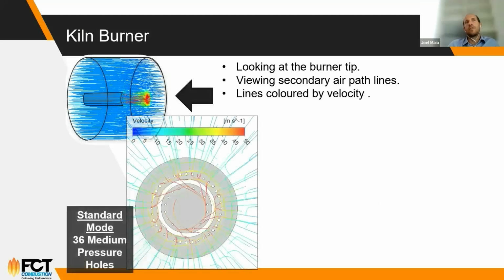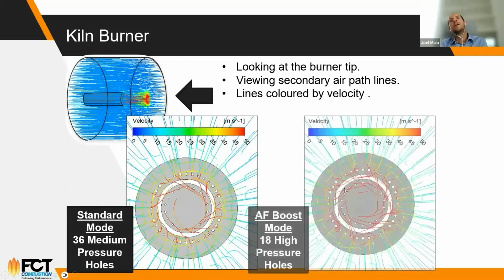To check about the secondary air, we made a cross-section in the kiln showing only the secondary air lines. Here would be in the standard mode, how much air you are sucking inside the flame. And here with the boost mode, you can see that you suck much more oxygen into the flame from the secondary air. It's a hot and high oxygen content air.